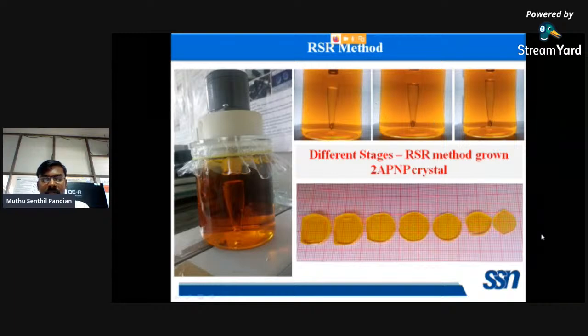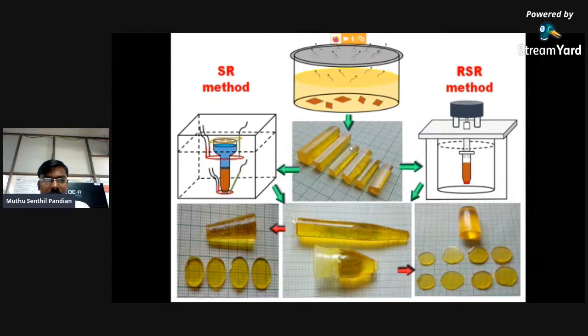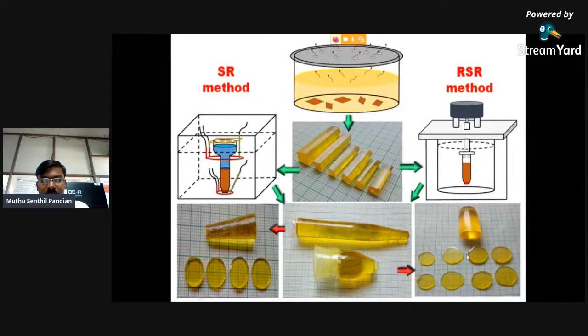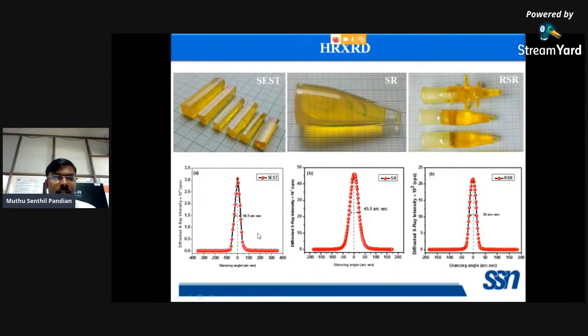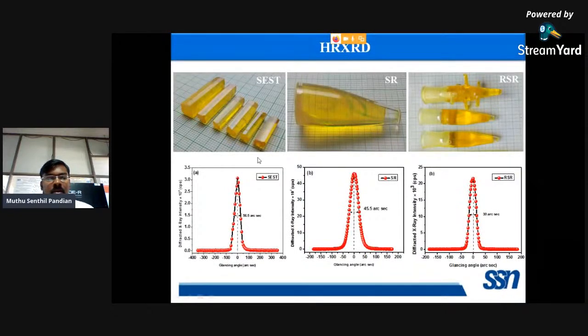This is the cut and polished wafers. So this is the crystal grown by conventional method, this is the crystal grown by SR method, and this is the crystal grown by RSR method. So the crystalline perfection of the conventional, SR and RSR methods have been identified using this high resolution X-ray diffraction. I already told you, for better crystalline perfection, the FWHM value of the material must be very low. It must be very single and sharp.